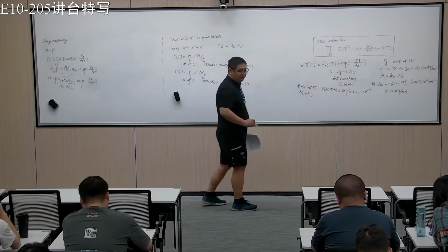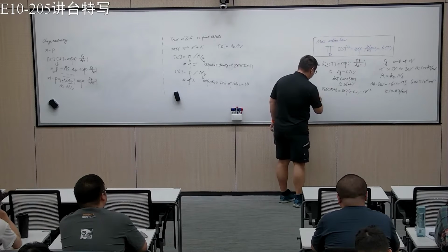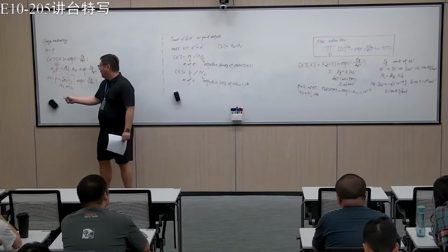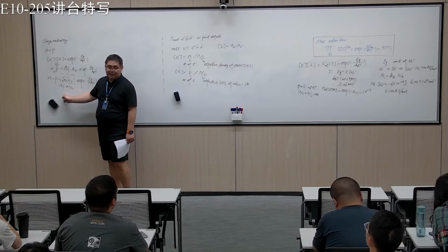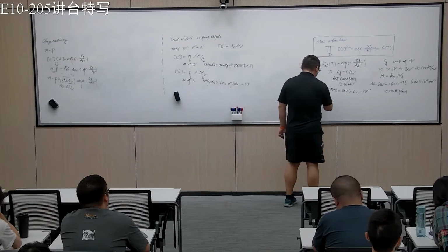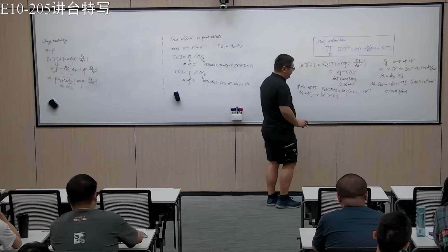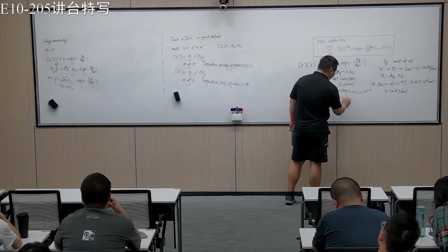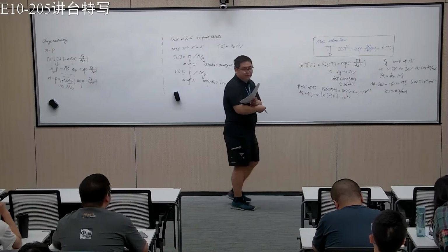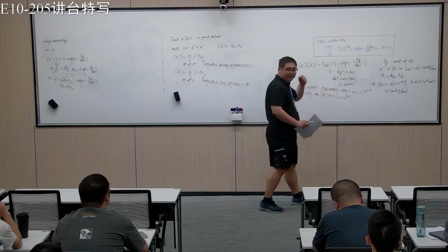So let's say here in the silicon case, if we say these are the same, okay. If we assume for a minute this is the same, then we know these two are the same, right? So these are 10 to the minus 8.5. Okay, so it's very, very small. It's basically at the parts per million level.